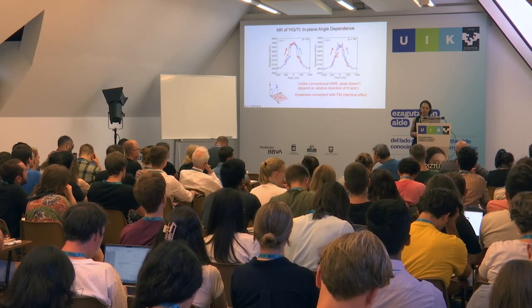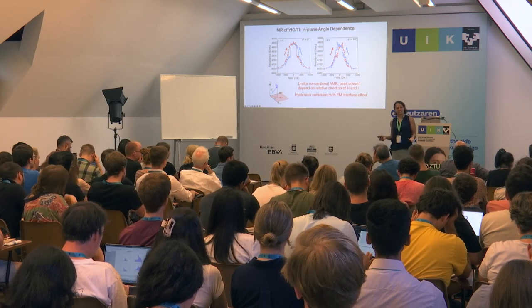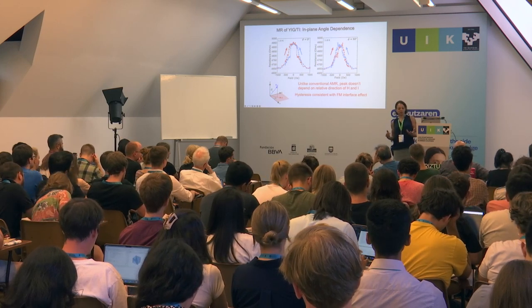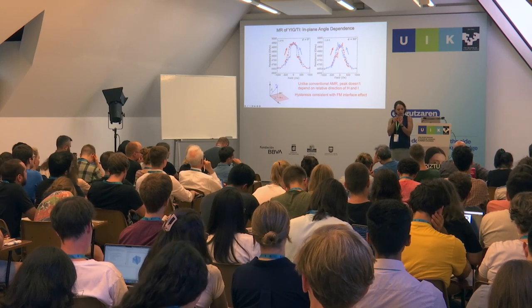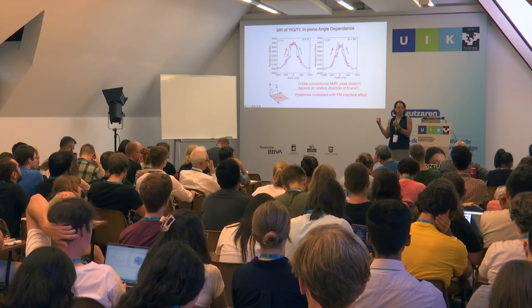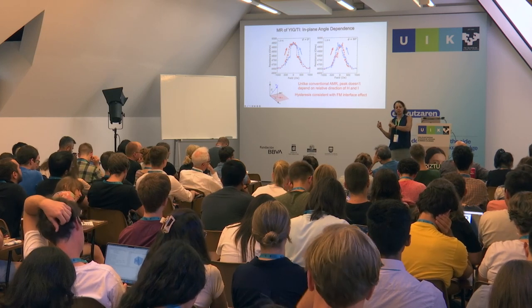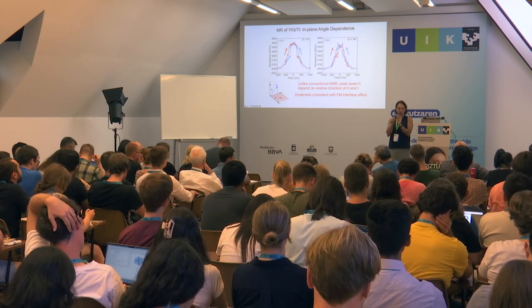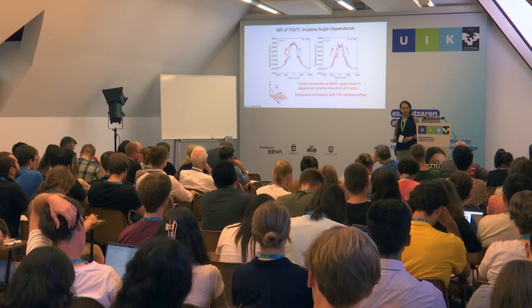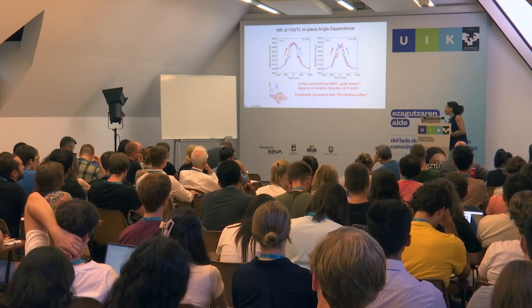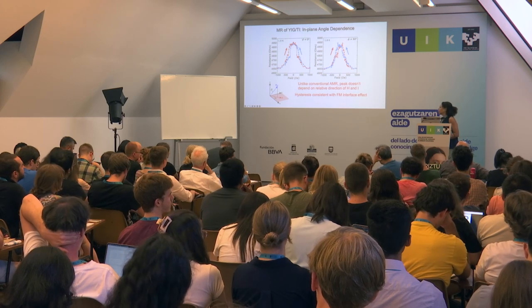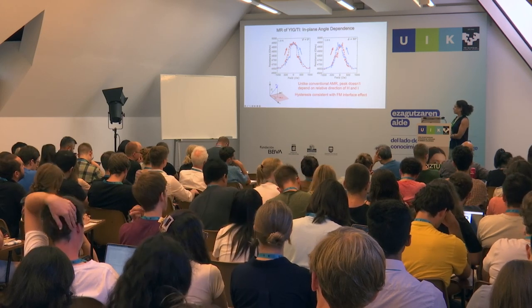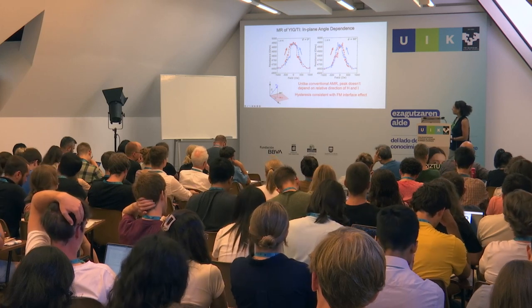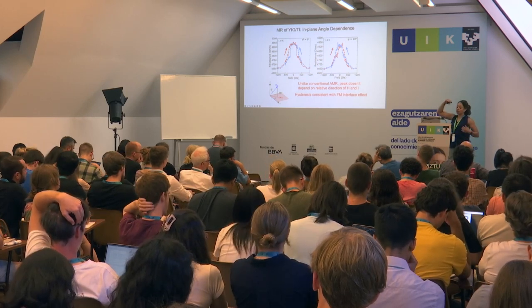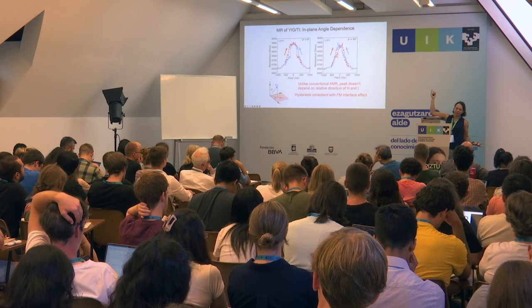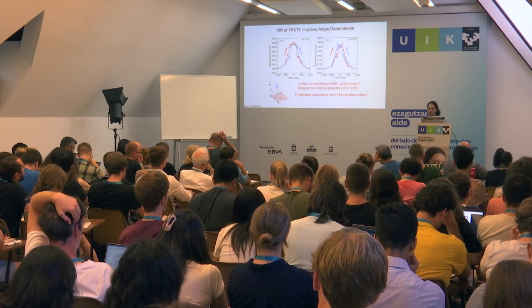Yes. So the reason we didn't do that is that if you measure this, at least in a magnetic property measurement system, you have to have a little crystal or piece of it. And these are patterned films. And so we couldn't do the same measurements of the patterned film that we could do with the little crystal of YIG, basically. But otherwise, you could measure that directly. Without measuring that directly, we just have to infer that the YIG is insulating, so any effects here have to be in the bismuth selenide, and there's something switching here at a much larger scale than ever switches in the YIG alone, right? You know, 100 times larger than the YIG.